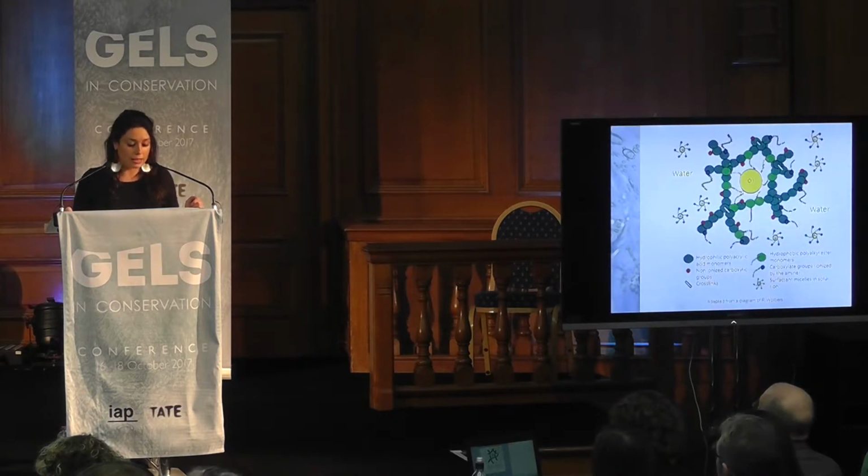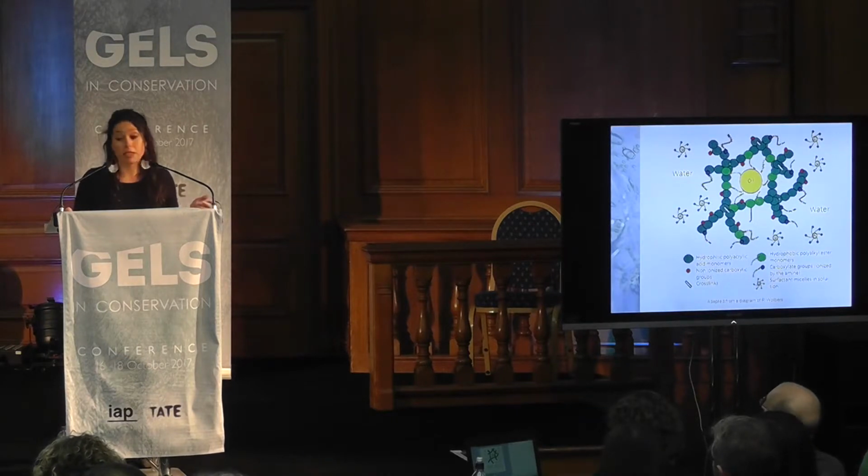When the polyacrylic acid is neutralized by amines, which are weak alkalis, the resulting species are partially dissociated in water and exist in both ionic and neutral form, as you can see on the picture. If present in sufficient amounts, free amine can form micelle-like structures that can offer supplementary emulsifying, solvent, surfactant, and chelating actions that could be very useful for specific cleaning tasks. But viscous amines, such as triethanolamine or Ethomeen, could leave residues.